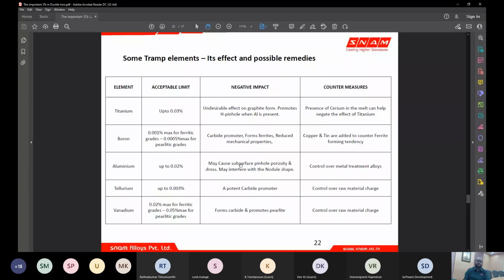And when aluminium is present, we know there is a tendency for aluminium to fix hydrogen from the moisture in the liquid metal and moisture in the mold, so it can lead to more porosity. So control over the treatment alloys, or the aluminium percent from your treatment alloys, can give control over aluminium. Tellurium, we know, is a very strong carbide promoter.